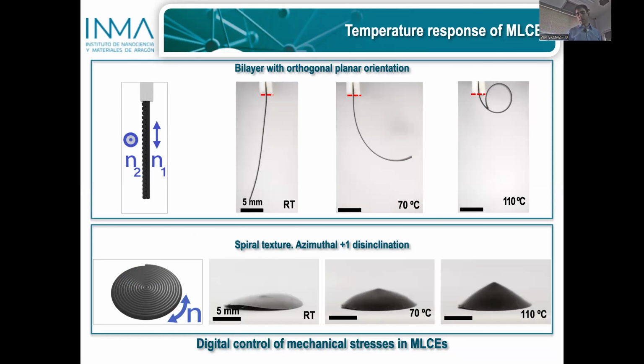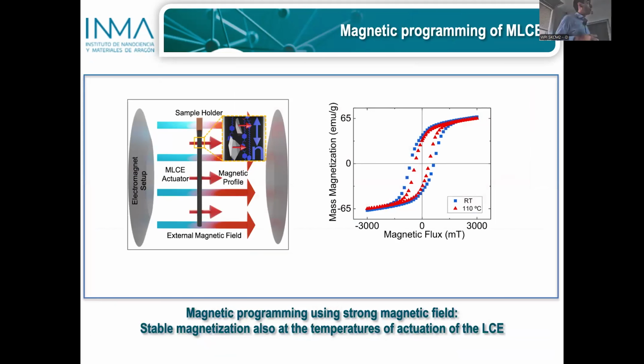So we are able to keep the typical mechanical deformation of the liquid crystal elastomer, but we have an extra degree of freedom in the actuation, as we have magnetic particles dispersed in the material that we can program with a strong magnetic field. If we now expose our film to a strong magnetic field, we magnetize the sample, we generate magnetic moments in the sample, and this magnetic moment is stable even at the high temperatures we use for thermal actuation. So in this system we can play with two stimuli, thermal and magnetic.